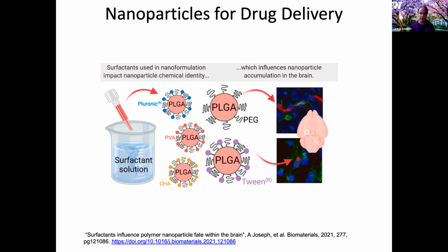And so we were working, this was actually Elizabeth Nance's group here at the University of Washington in the chemical engineering department. They're doing great work with these nanoparticles, but they were having trouble proving that their surfactant, which is what they thought was affecting this process, was sticking to the outside of the nanoparticle. So we were able to characterize that with TOF-SIMS, not something you can do with many other techniques like XPS, because PLGA and PEG have very similar atom percentages, and it would be difficult to pick out with techniques that were just monitoring atoms or even bonding environments.